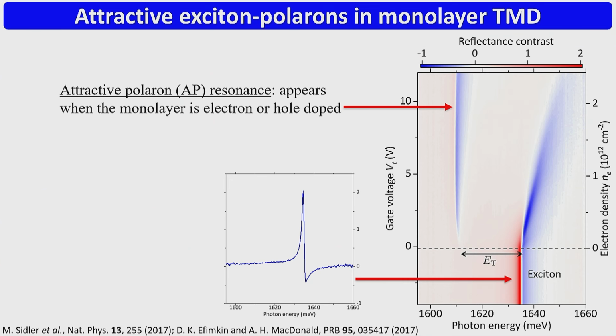So here is a gate scan of a monolayer in this case. Basically, when there are no carriers, we have an excitonic resonance. If I take a line cut, so this is a heat map, there is a resonance that is nice and narrow, but not terribly interesting. Now, when you inject the electrons, then the spectrum changes. So the exciton interacts with the electrons and tells us some information about the electronic system, like what its effective mass is, whether it is incompressible, etc., etc.